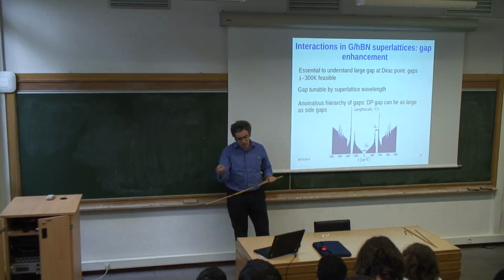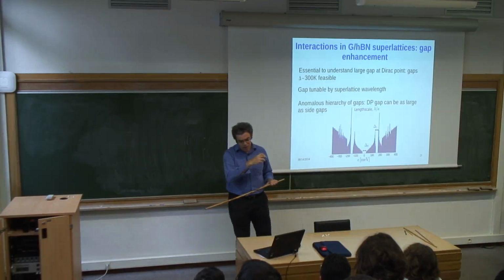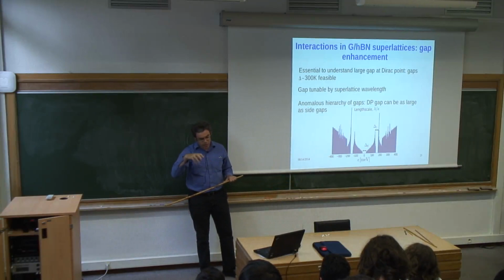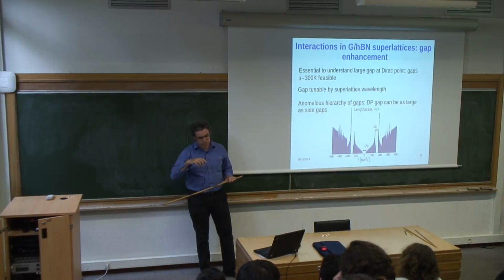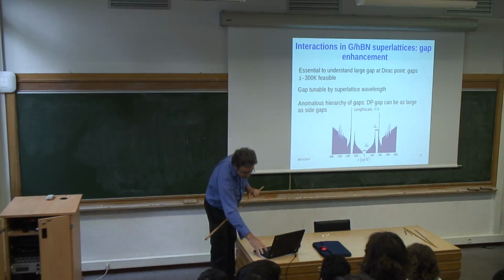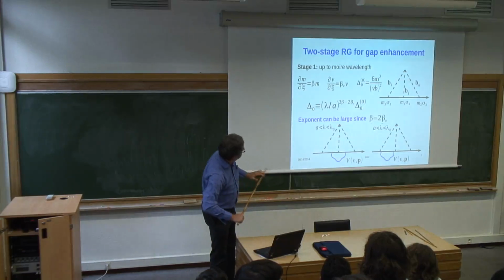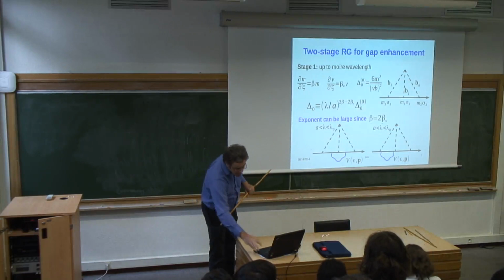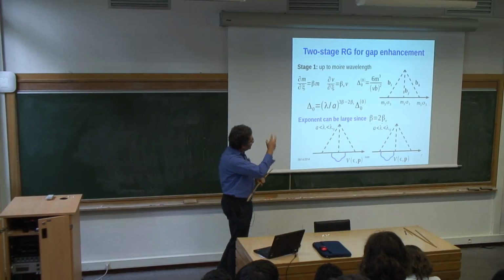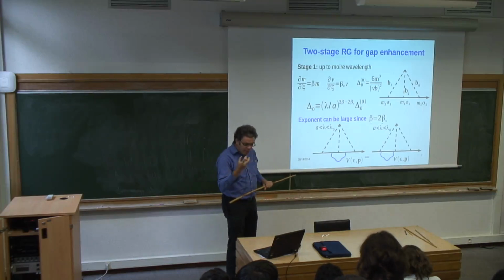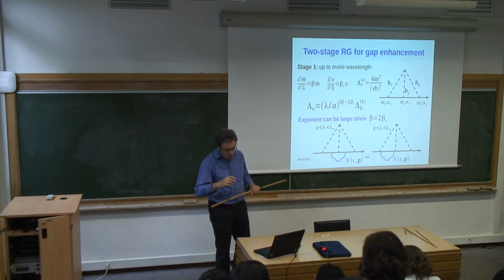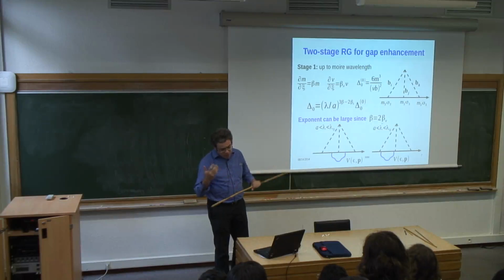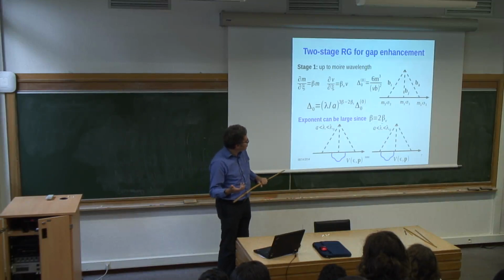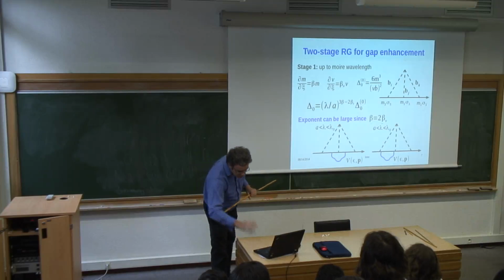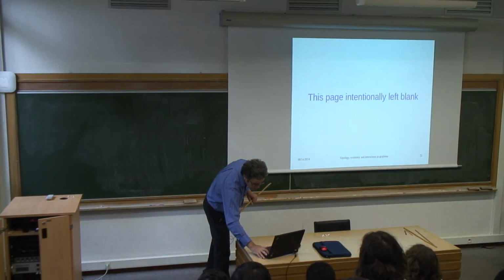And I think the reason is that even though there are terms involving different valleys, the interaction effects, because of long-range Coulomb interaction, don't couple valleys. So because of that, all renormalization proceeds in the same way. Mass is spatially uniform. If it's not spatially uniform, then you have this more complicated story. And here it's actually interesting because of perturbation, going to third order perturbation theory, your bare non-interacting gap is smaller, but then renormalization proceeds faster, and somehow these two effects nearly compensate each other, and the resulting gap you predict is comparable to what you would get for spatial uniform modulation. Yeah. Okay.